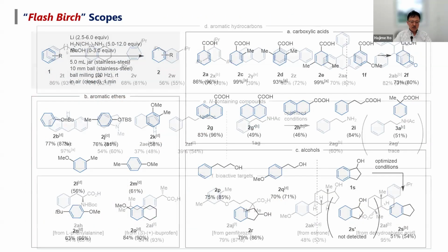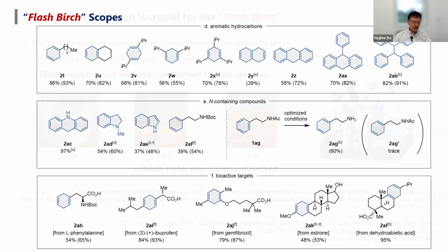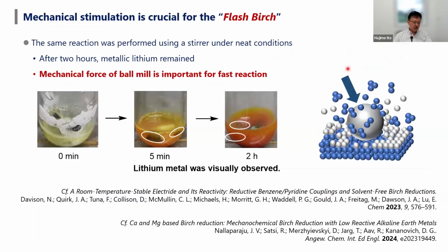We also conducted test tube reactions using the same additives, substrates, and lithium. But after 5 minutes, almost all the lithium remained. Even after 2 hours, some messy reduction could be found, but all the lithium still remained.